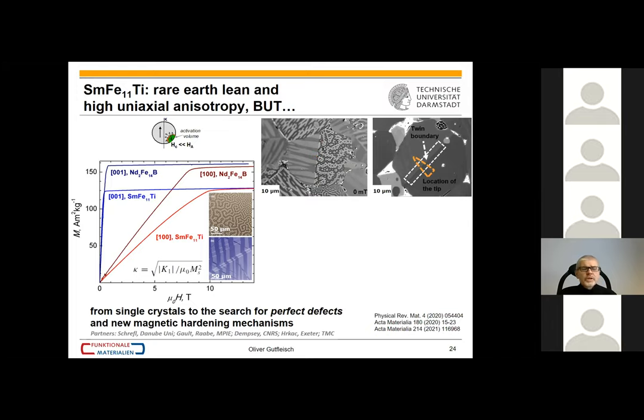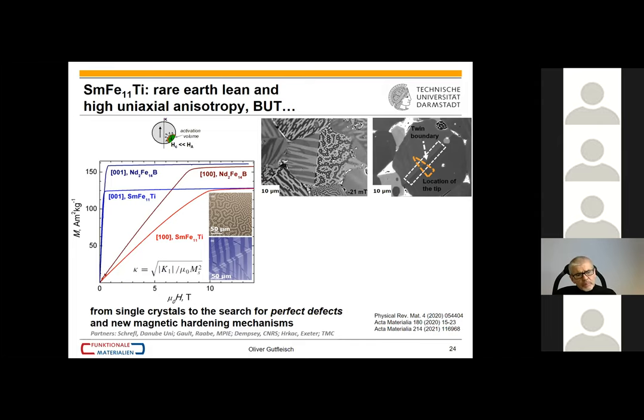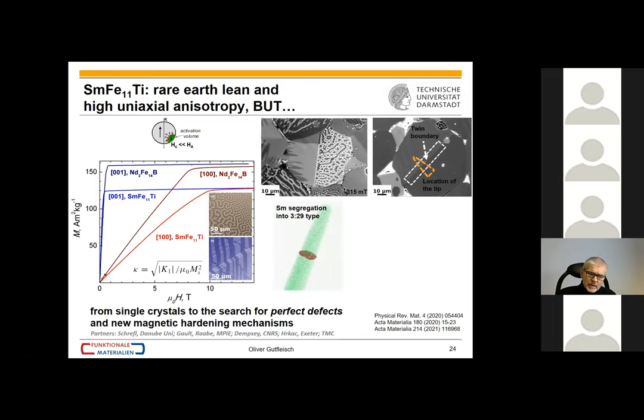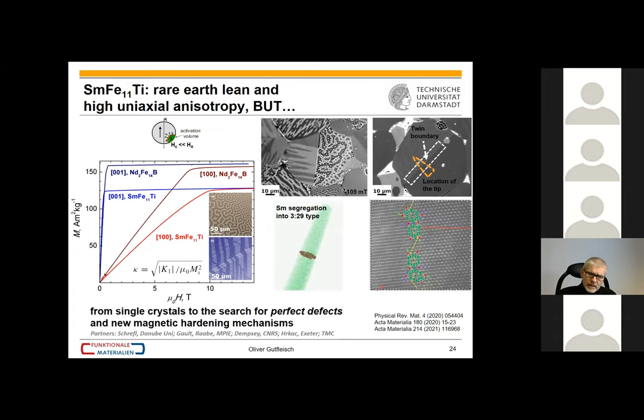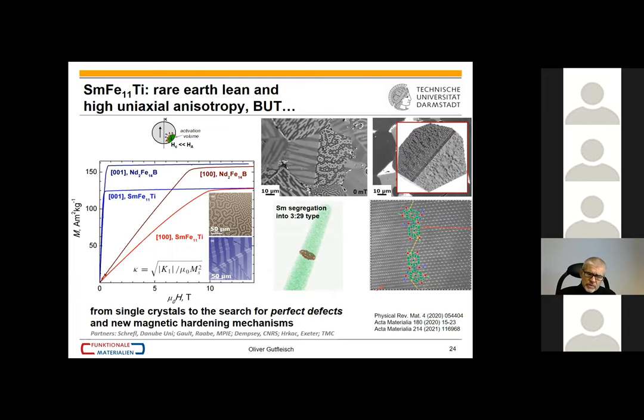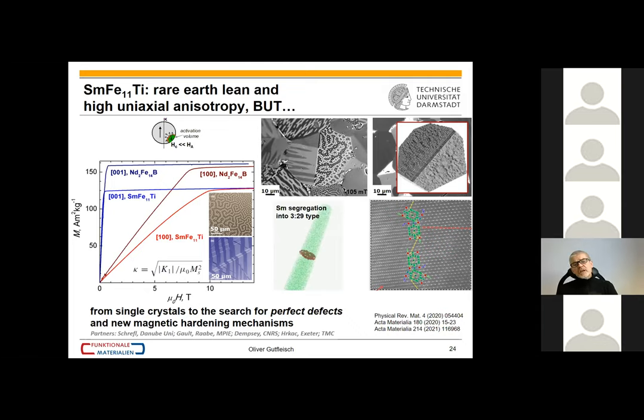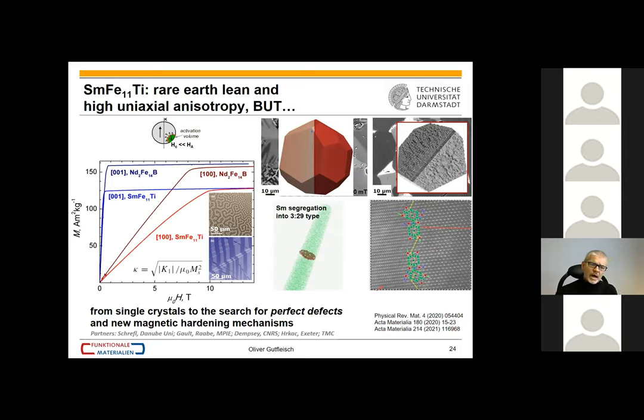And then if you look with a Kerr microscopy, we can see under the applied magnetic field that the magnetization reversal is now not nucleating at the grain boundary as you would expect, but is nucleating and propagating from the twin boundary. And that actually shows us that we have here now a new weak link. And we try to understand this again. We prepared by FIB this twin boundary for atom probe. It could be then analyzed further by high resolution transmission electron microscopy again, so that we can see it's a 3:29 structure type, three-dimensional object actually. And Thomas Schrefl then also did some micromagnetic simulations and could show how strong the effect is of the twin boundary on the coercivity, how efficient it is to kill anisotropy.